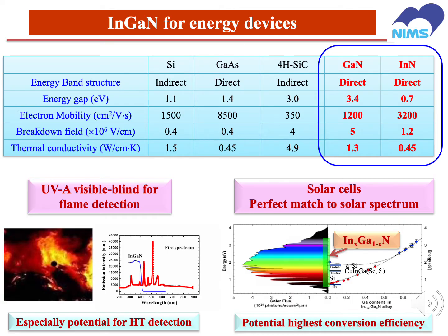At first, I will introduce the material indium gallium nitride for energy devices. This figure shows a comparison of InGaN to silicon, gallium arsenide, and silicon carbide. Compared to silicon and silicon carbide, InGaN is a direct bandgap material, so it can have a high quantum efficiency, and the energy bandgap is higher than silicon, so it can have a high breakdown voltage. The electron mobility of InGaN is also very good.